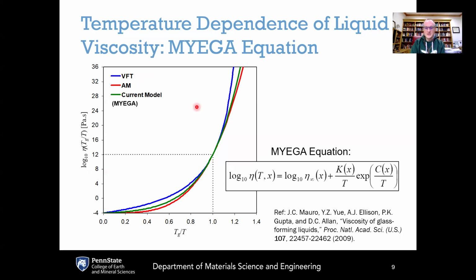So one of the advances that have been made since then was the introduction of this MYEGA equation by these authors back in 2009. This equation gives a more accurate description of the shape of the viscosity versus temperature curves for the liquid state. And you can see here the VFT model is being shown in blue. And if you consider the same glass transition temperature and the same fragility index, the MYEGA equation is being shown in green, and the curvature is somewhat less.